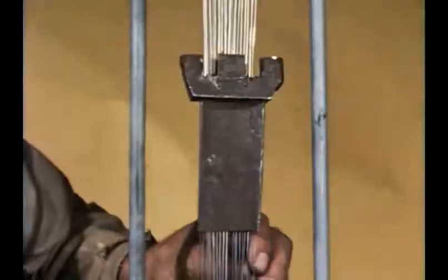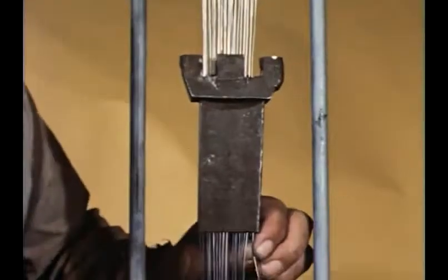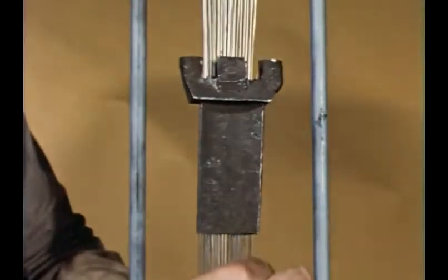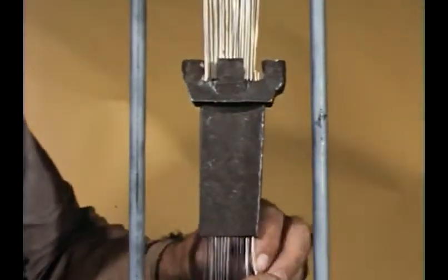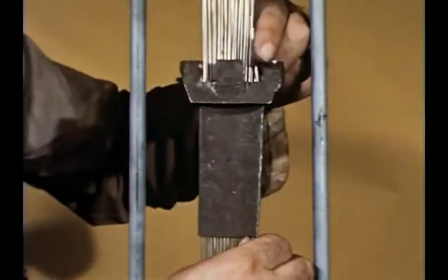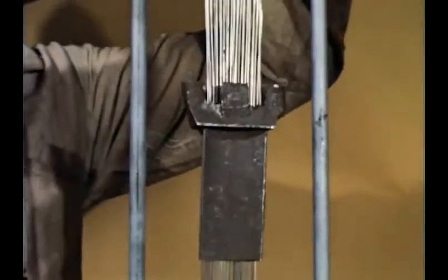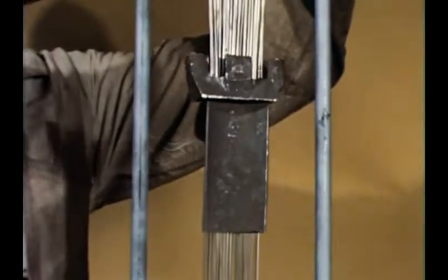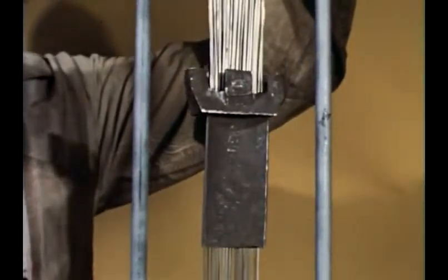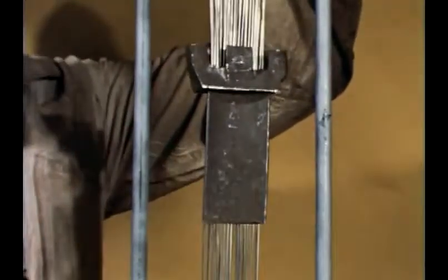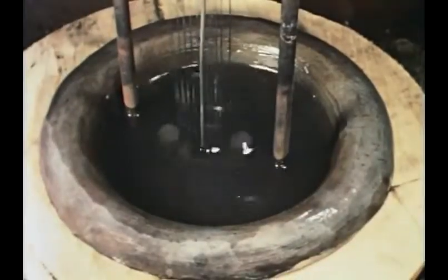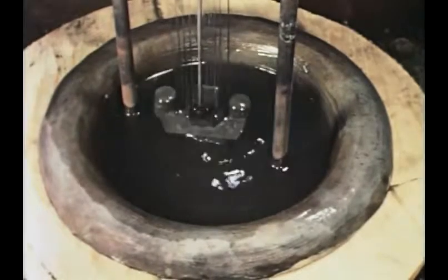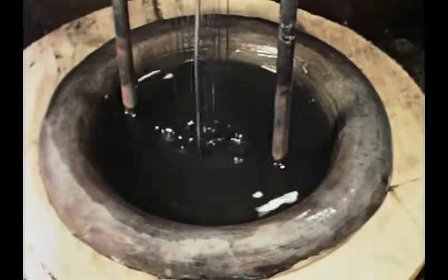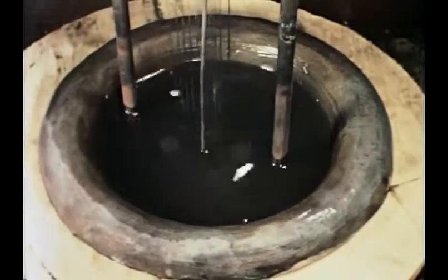After the casting is cleaned up, the ceramic tubes used to form the cooling passages in the blade must be removed. This is done by threading fine stainless steel wires through each ceramic tube and stretching them taut on a frame. The turbine blade is then attached to a cam device designed to slide the blade up and down on the wires. The lower part of the assembly is then immersed in a bath of molten caustic. This helps to remove reaction products and introduces fresh caustic to the bore of the tubes, and hence accelerates the solution and removal of the core tubes.